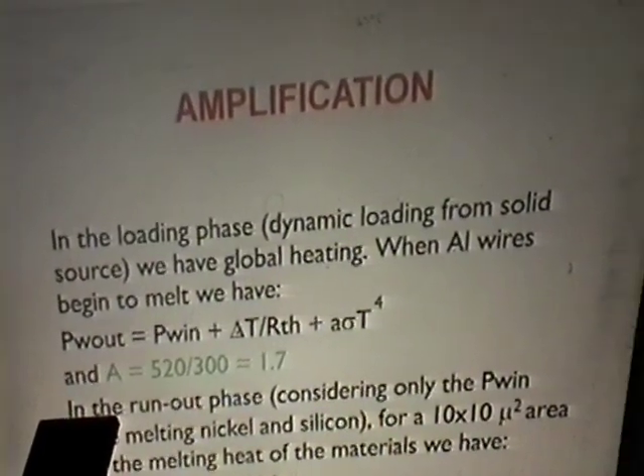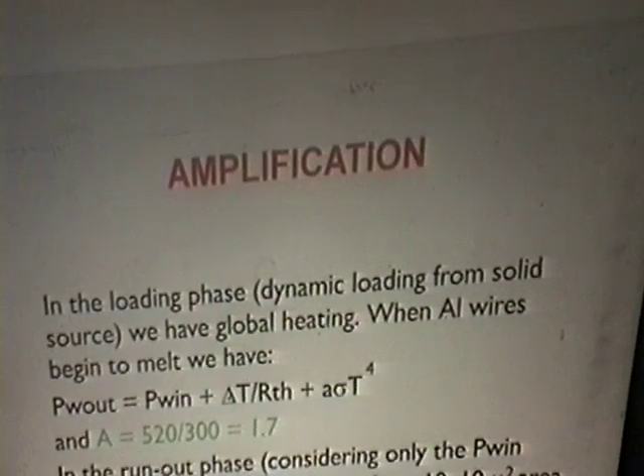And during one experiment, we had an increase of temperature of the sample without this distraction. So we can calculate the amplification at that point, stopping the experiment, because we saw that the aluminum used as bonding began to melt. The melting temperature of pure aluminum is 660 degrees, and we could calculate the amplification in that case, and we had 1.7. In the case of run out of the reaction, because we cannot stop the reaction easily if we don't have the feedback, we calculated amplification of about 10.